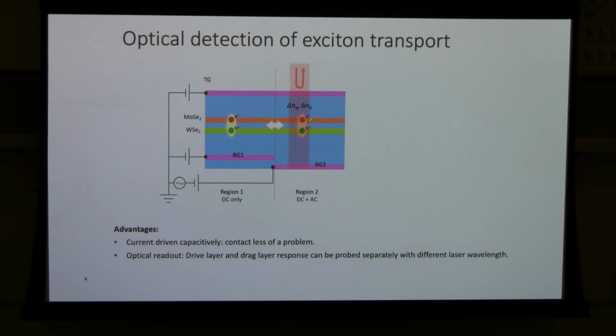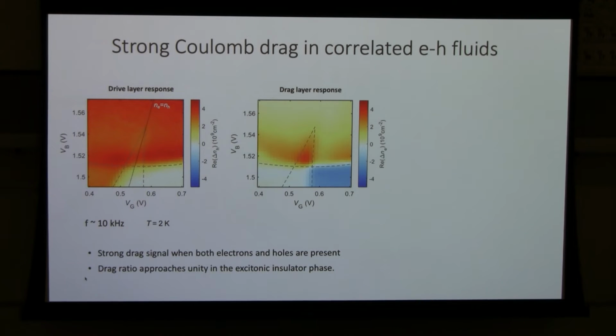the local electron density as a function of position and as a function of time or frequency. So in this case, we can see how electron density is changing and how hole density is changing. That basically tells us the electron current and hole current. And we can see whether they are correlated and how they correlate with each other. Okay, so here we just measure with 10 kilohertz modulation of the gate and measure the induced change of electron density and hole density, which will be correlated to the induced electron current and hole current.